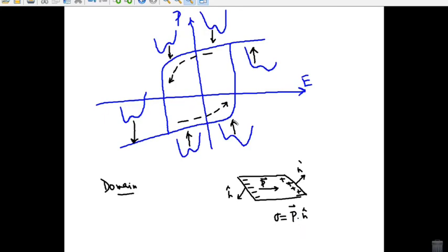The system will minimize its energy by abolishing, as far as is possible, the surface charges, and in a thin film, for example, this makes clear that the preferred orientation of the polarization will be lying down in the plane of the film rather than pointing perpendicular to the film. So if one has a crystal that is thick in all dimensions, another situation is preferable to introduce the domains where the polarization is oriented to be always parallel to the crystal